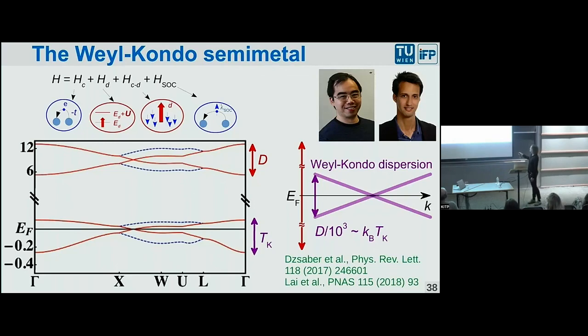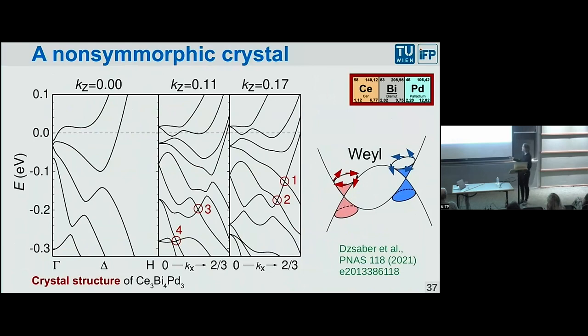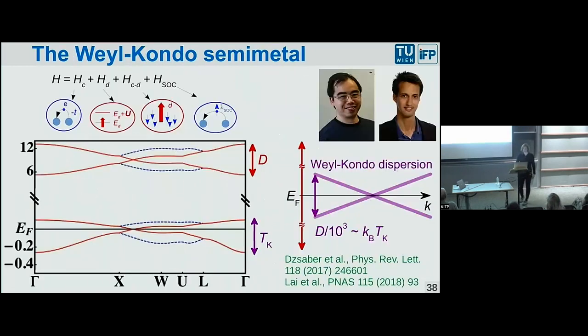Or in other words, the interaction effect makes it so that from bandwidths of the order of an electron volt, this wild dispersion now becomes extremely flat and of the order of our 10 Kelvin Kondo temperature. So that's what we have to accept, right? The interaction takes these crossings from where they are in the band structure and puts them at the Fermi energy in an extremely flat band. And that will apparently amplify the effect.